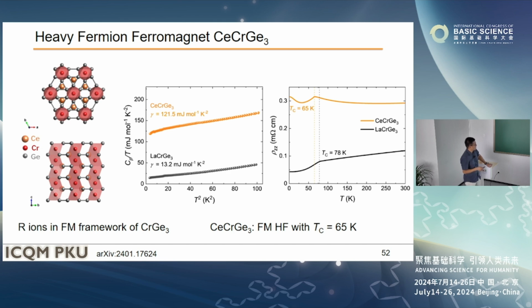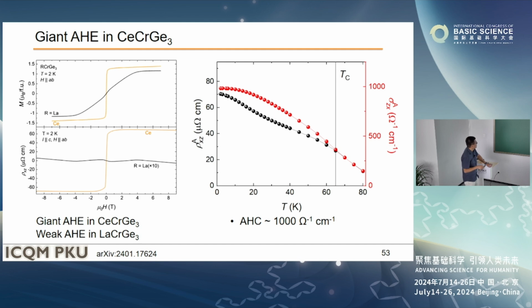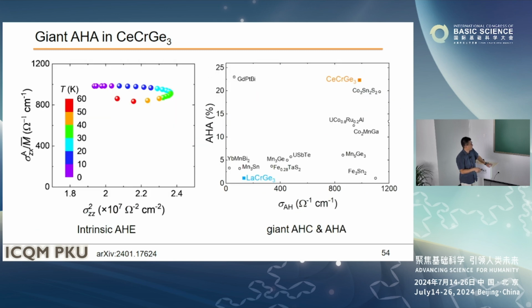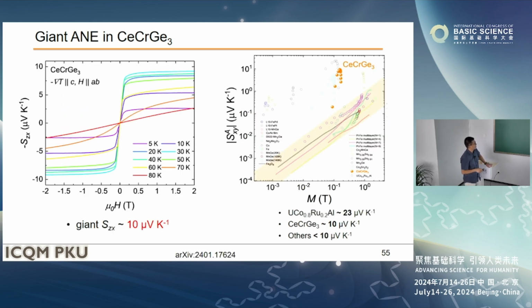Also, there is a large enhanced gamma. And what we found is although these two compounds have a very similar saturated magnetization, the anomalous Hall effect for the cerium compound is over 100 times larger than the lanthanum compound here. And we plot this anomalous conductivity, which is basically intrinsic, and also the anomalous Hall angle and anomalous Hall conductivity give a record value for this compound, which is even larger than most of the compounds we know, as far as we know. More important, we also measured the Nernst effect, and this Nernst effect is as large as 10 microvolt per Kelvin.